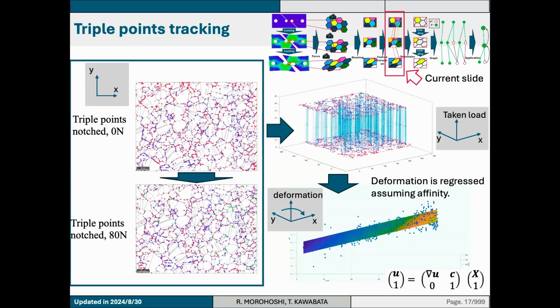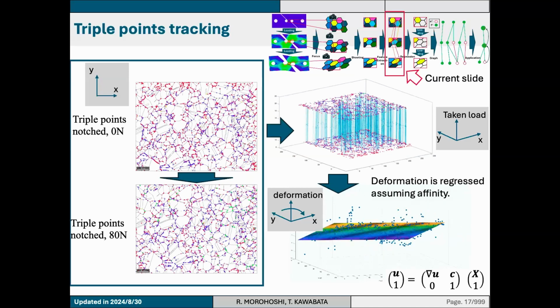And let me introduce much more about the post-processing process. This is the triple point. We identified all the triple points at each load, and we identified which triple point corresponds to which triple point on another load, in a way that I omitted because the time is limited. But anyway, by doing that, we could identify the deformation of each triple point, and then we regress the deformation of the triple points into any coordinate, assuming the affinity. I mean the linear regression. So the next slide shows whether the affinity regression is enough or not.